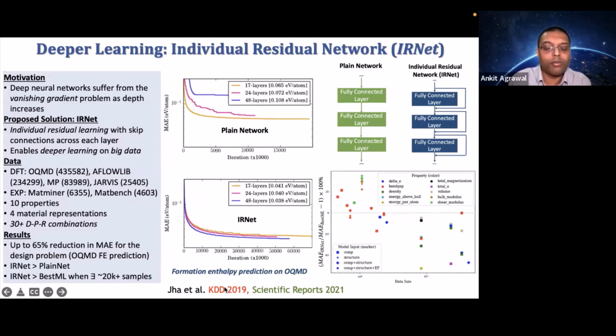And then a couple of years ago, we got this KDD publication based on this work. And some of you may know that KDD is the topmost data mining AI conference in our field. And very recently, we did a thorough evaluation of this model on materials data sets from big data sets, 400,000 plus, to small data sets like experimental 4,000 and so on, with 10 different properties, as you see here, and 4 different material representations: composition, structure, composition plus structure, and composition, structure, and elemental fractions all combined. In total, we had more than 30 different data set, property, and representation combinations, and that allowed us to do a thorough evaluation of how this model is behaving.